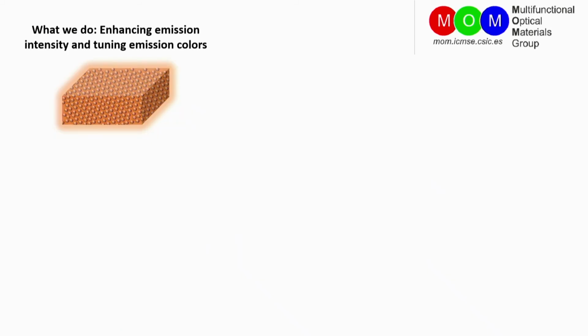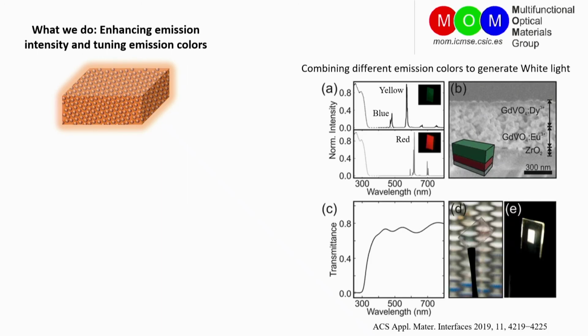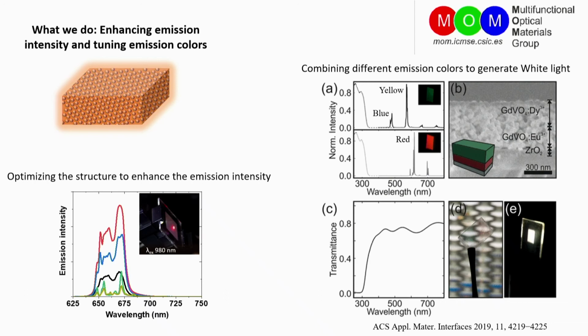We have seen that phosphor particles are very important. They can be applied in many different fields. So what we do at the Institute of Materials is enhancing the emission intensities and tuning the emission color. For instance, I will combine two different types of phosphor particles, in which one has blue and yellow emissions, the other one has a red emission. By adjusting the intensity ratios of those emissions, we can generate a white light. We're also focusing on the optimization of structural properties of the particles in order to maximize the emission intensities.